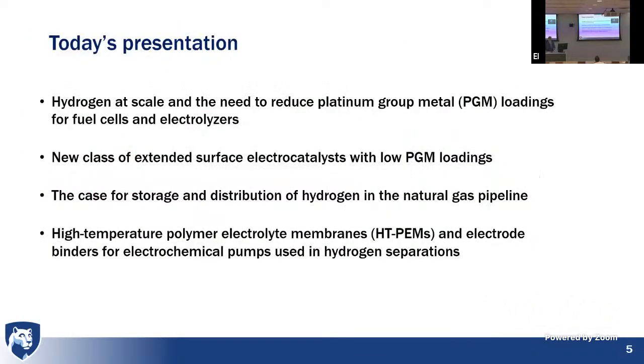All right, so I want to tell you about hydrogen at scale and the importance of reducing platinum group metal loadings in those technologies, really for them to grow and proliferate. And then I'll tell you about a new class of extended surface electrocatalysts with low platinum group metal loadings. So this is borrowing ideas from block copolymer nanoscale lithography to get nano-structured electrodes that have, I would argue, maybe competitive state-of-the-art data. Then I'll transition to a new area in my group where we're looking at putting hydrogen in a natural gas pipeline to reduce the cost for hydrogen transportation.